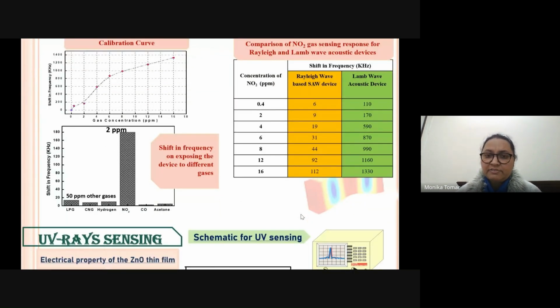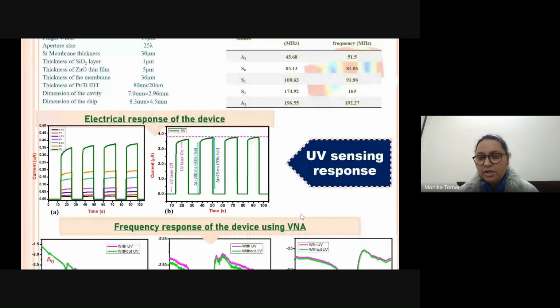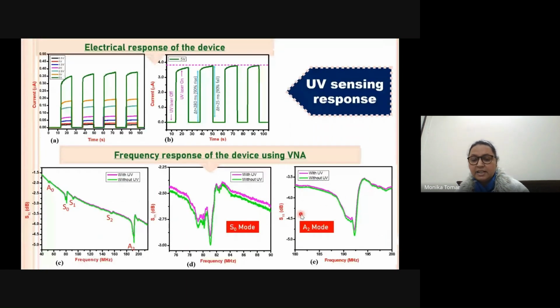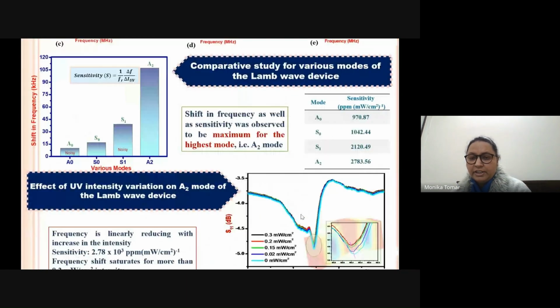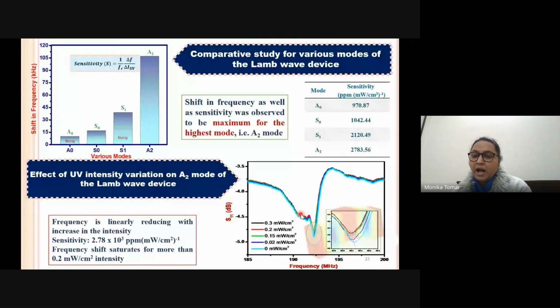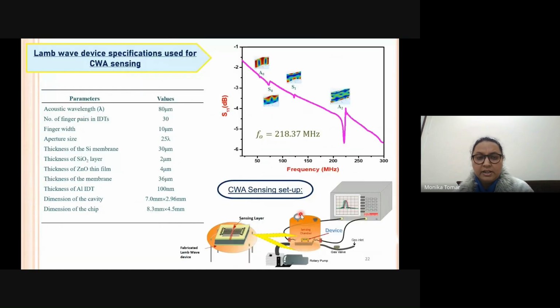Then we utilize these devices for UV ray sensing also, and we find that the devices are highly sensitive towards UV radiation, specifically the higher modes, which show very high sensitivity, and the sensitivity value is much higher compared to those reported in the literature.